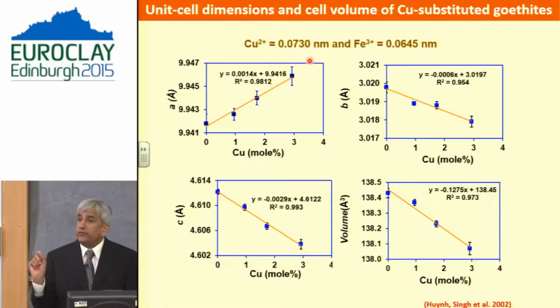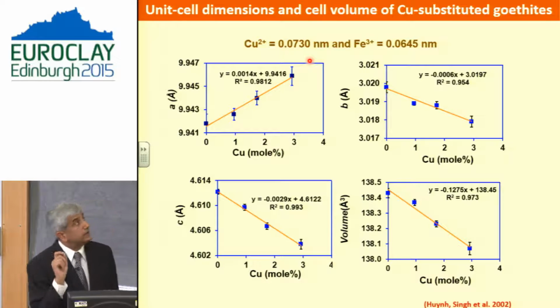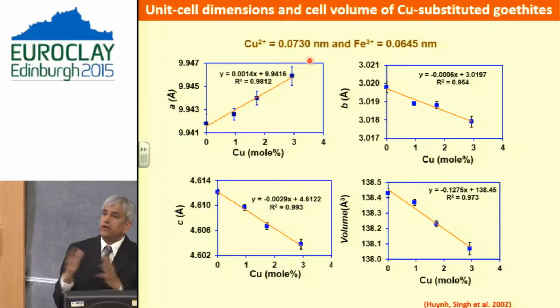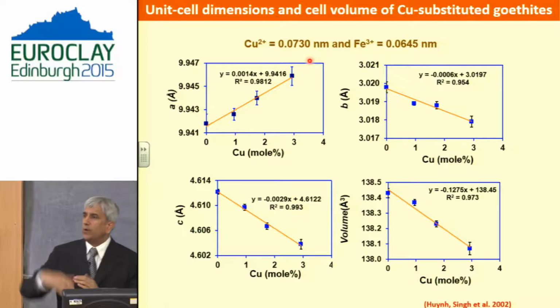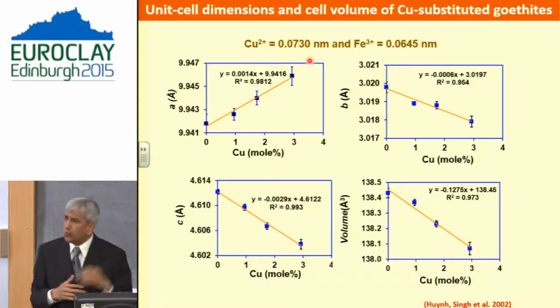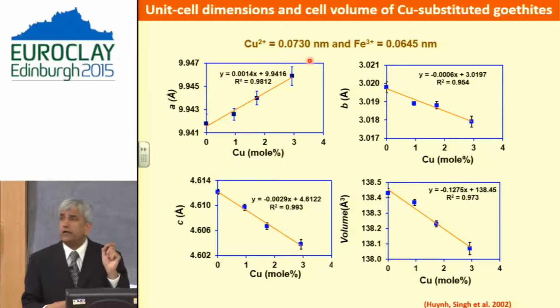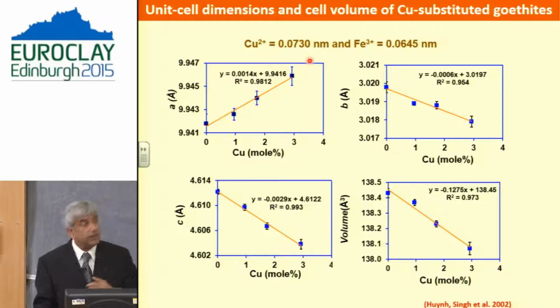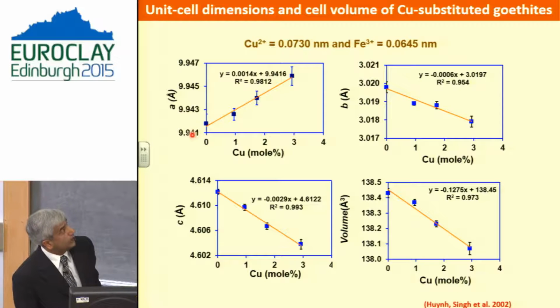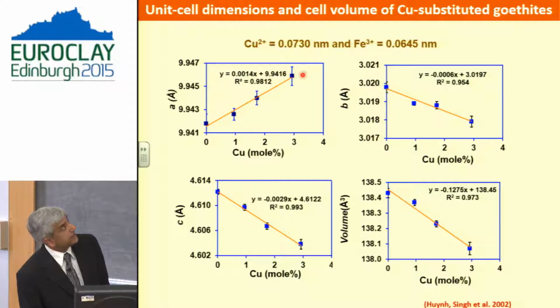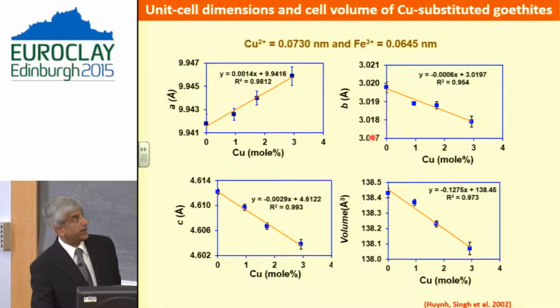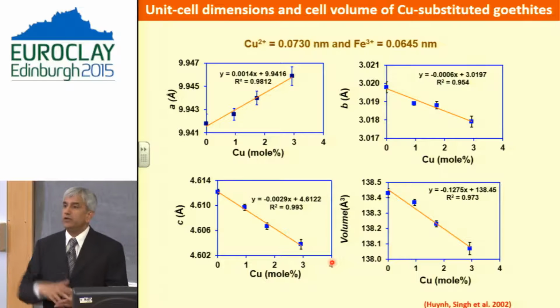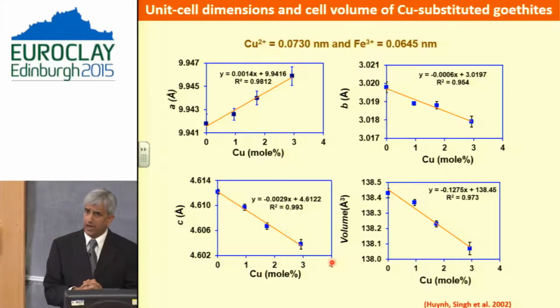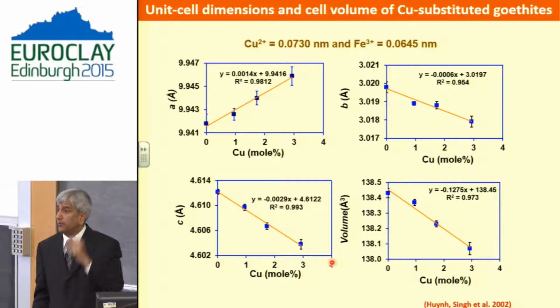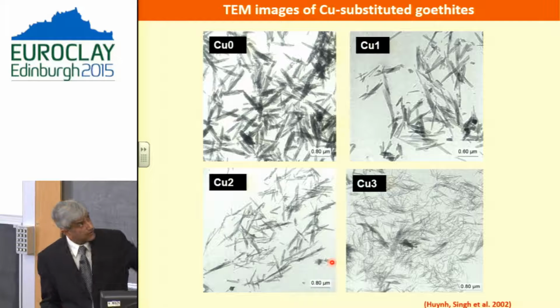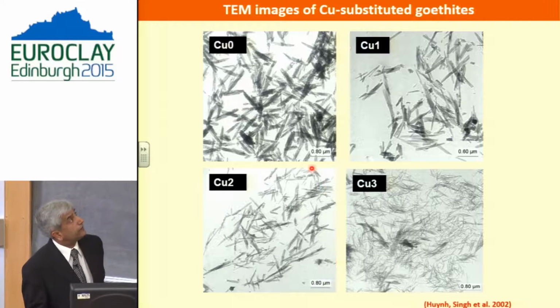Although the size of copper is larger than ferric, the unit cell dimensions are not increasing as you would expect, or as you saw in case of cobalt, where all the dimensions were decreasing. Copper has what we call a Jahn-Teller effect, so the octahedra get distorted and the effect is different. Only the unit cell parameter A is increasing with the increasing size, whereas the dimensions B and C decrease. So the octahedra get highly distorted as a result of the small amount of copper in the structure. That's quite evident in case of copper.